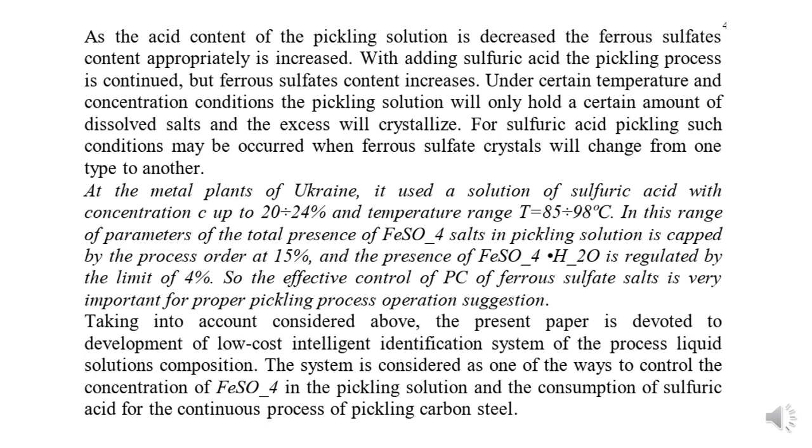So the effective control of the PC of ferrous sulfate salts is very important for proper operation of the pickling process. Taking into account the above, the present paper is devoted to the development of a low-cost intelligent identification system of the process liquid solution composition. The system is considered as one of the ways to control the concentration of ferrous salts in the pickling solution and the consumption of sulfuric acid for the continuous process of pickling carbon steel.